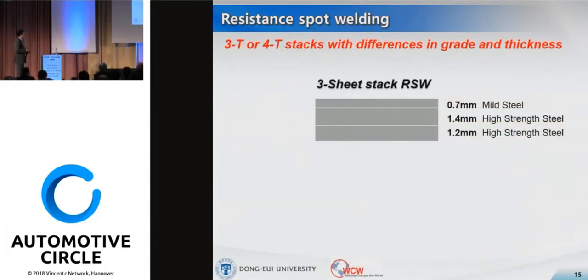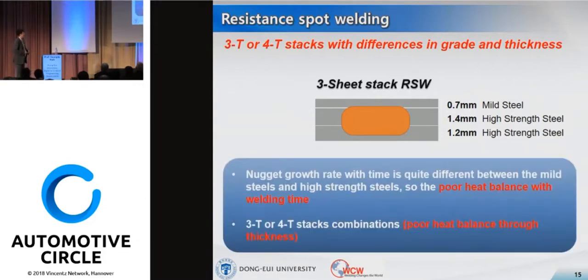In case of resistance spot welding of a three-sheet or four-sheet stack with different grade and thickness, this is the same thing as introduced. A very thin mild steel, 0.7 millimeter, with high-strength steels. So mostly heat will be generated by the high-strength steel side, and this is what happened in here. Most of the heat is there, and it is not able to reach enough heat to melt the thin mild steel side. But the nugget showed quite good promise for good joining strength.